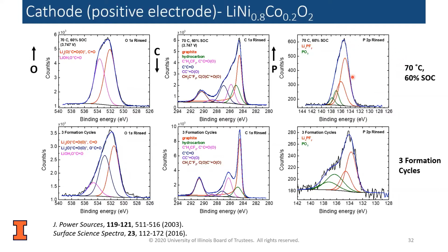And this pretty much indicates why you should not leave your laptop plugged in all the way, because if you hold your battery at a high state of charge for extended periods of time at elevated temperatures, you're just accelerating the aging and you're taking life out of the battery.